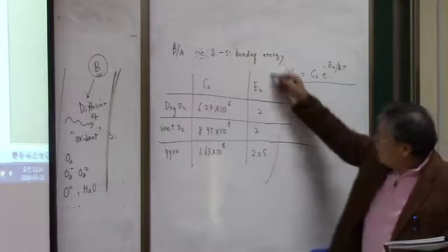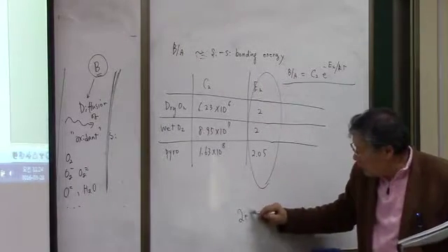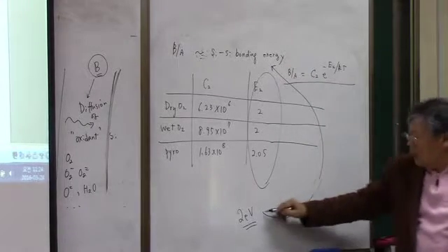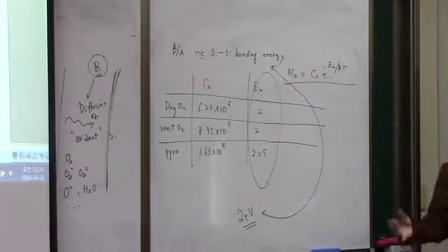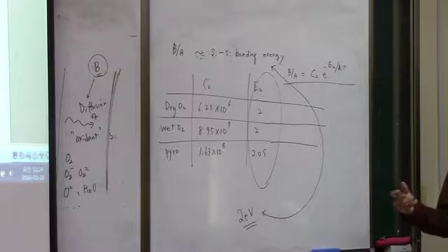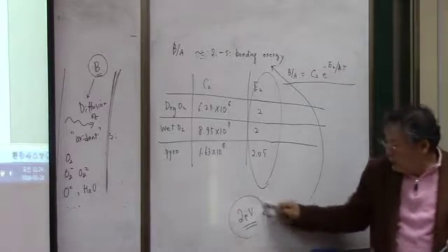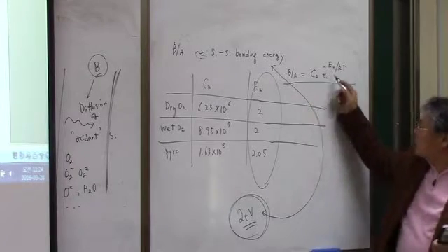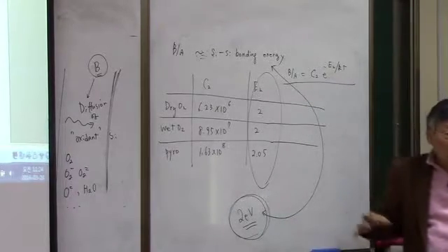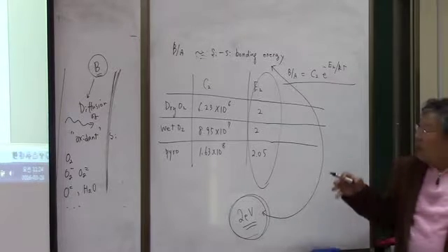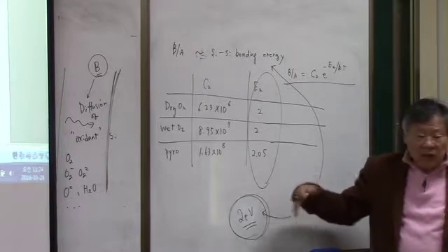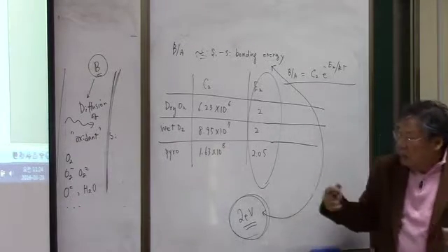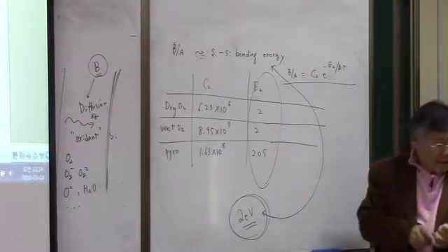By the way, this 2 electron volts is really the bonding energy of silicon. So this fact, that the activation energy is about 2 electron volts, reflects the fact that this oxidation process is really related to the silicon bonding.